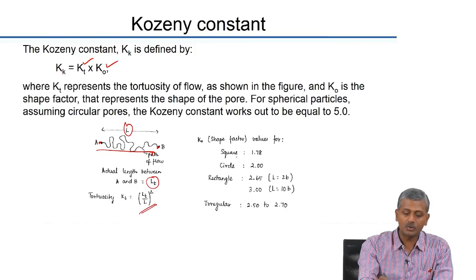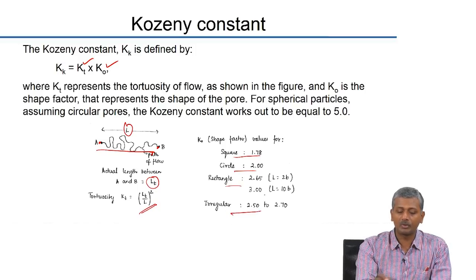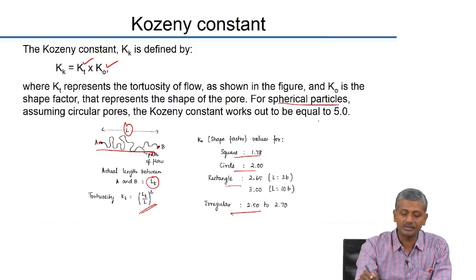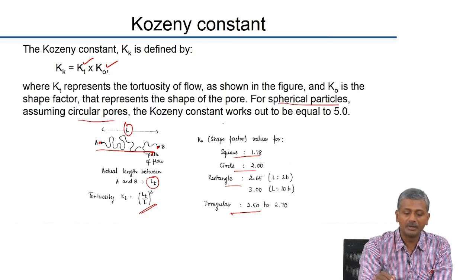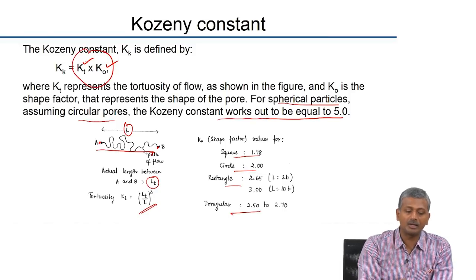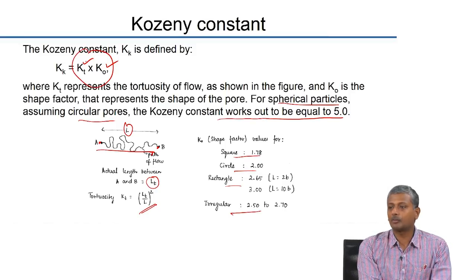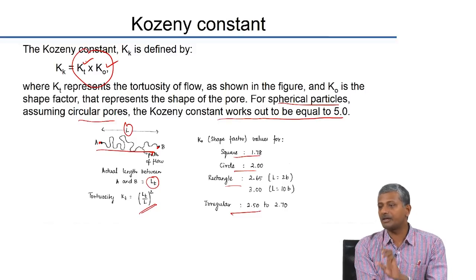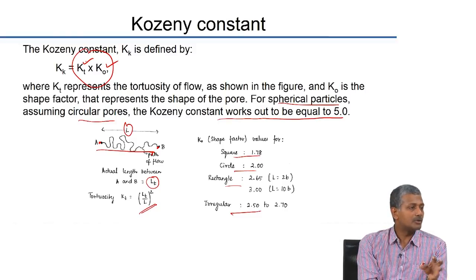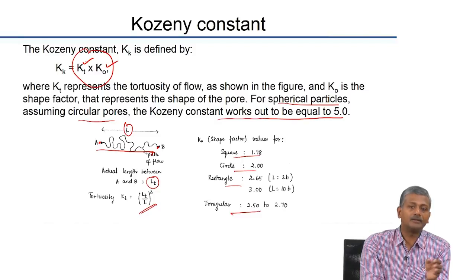The shape factor depends on the shape of the porosity. If you have a square shape or circular shape or rectangular shape or irregular shape, you get different types of shape factors. Now generally for spherical particles, assuming circular pores, the Kozeny constant works out to be 5. That means the multiplication of KT and KO works out to be 5.0 for spherical particles. If you make an assumption of spherical particles, your system gets much more simplified and then you can relate directly the permeability to the porosity.